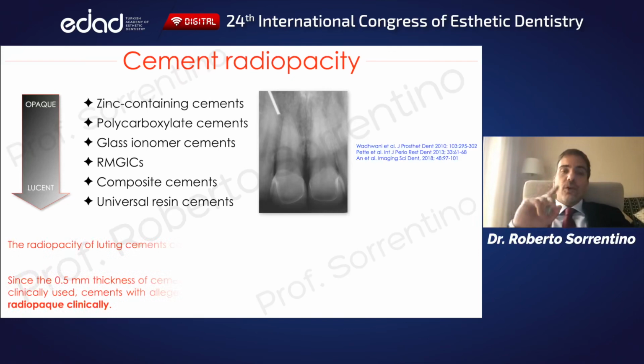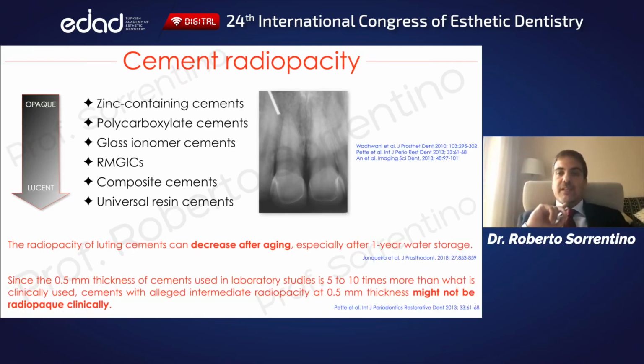It is worth noticing that cement radiopacity can decrease with aging, and that the cement film generally used in laboratory settings and in manufacturer's quality controls is 5 to 10 times thicker than it is used clinically. As a consequence, there could be a radiopacity mismatch between technical specifications and the real clinical performance of the cements.